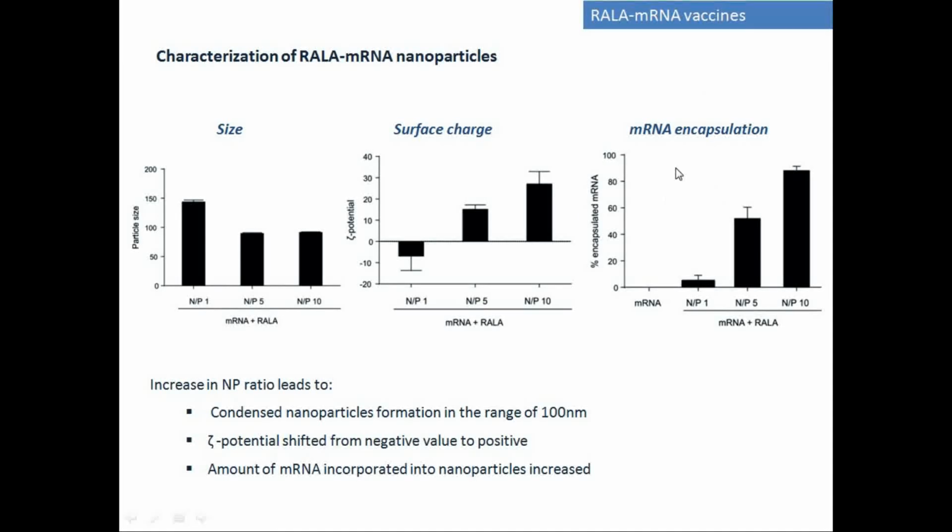Finally, we can look at your mRNA encapsulation. When comparing different formulations, at NP10 we can see that nearly 100% of the mRNA can be incorporated into the nanoparticles. Therefore, for the further studies, we have used this formulation, NP10.